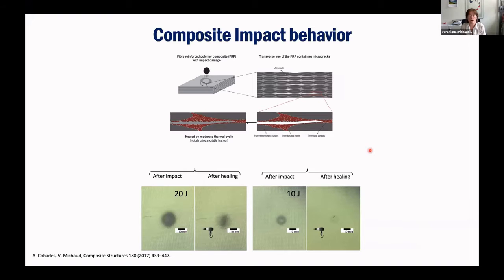In real cases, the wind turbine blade has an impact, and you want to heal after impact, so you don't need to fill the crack because the crack is very small. So we decided to do impact testing, and we used different impact energies. It was always between 20 and 10, and we went up to, I think, 40 joules.